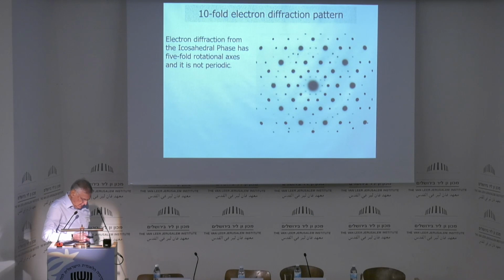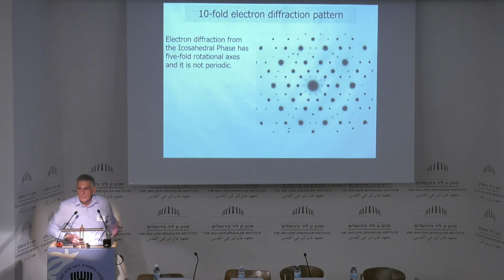Okay, let's go back a little bit. I look at this pattern, and I said, wow, that's very different. What's going on? What is the rotational symmetry? 1, 2, 3, 4, 5, 6, 7, 8, 9, 10. Oh, no, cannot be. 1, 2, 3, 4, 5. Tenfold, all right? Turns out that it is really fivefold, but you cannot tell from the diffraction pattern. You have to take later on, as I did, a Kikuchi pattern, and that tells you that it's really fivefold. But that's beside the point at this moment.